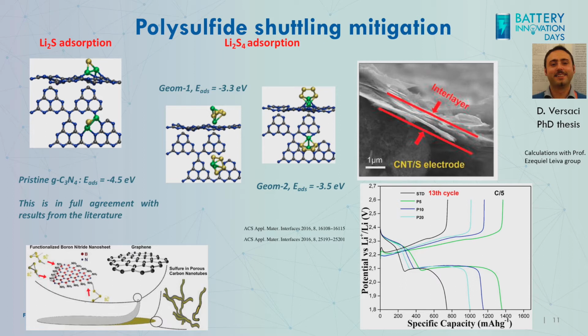I think that in particular the new generation will have very interesting and new ideas, but then we have to prepare them. And in my opinion, we cannot consider that now we are building gigafactories and in a few years we are destroying everything, starting again from completely new technologies. So if we can get something that we can combine and use, at least partially, what has already been invested, this is good. And sulfur can be a good solution because the production of the cathode can be not completely different. So the idea here is the use of a layer that you can see here to put directly on the cathode. You produce the cathode with maybe a roll-to-roll method that's commonly done for lithium ion, and then you can put this layer.